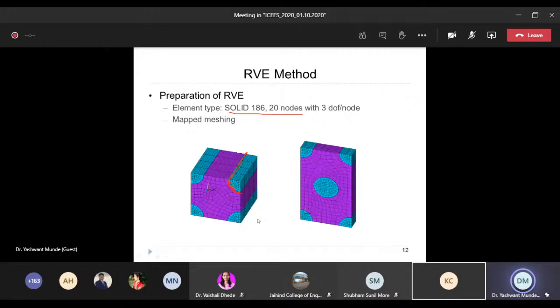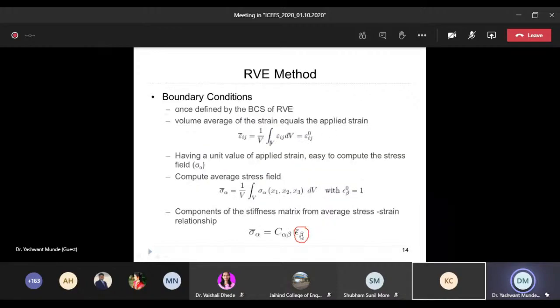And in a unit strain problem, we directly know the stress induced in each element, so then we can find out the value of C alpha beta. So what is the value of this strain? Strain is unit. We can know the stress induced in the RVE, and from the stress induced in the RVE, we can directly calculate the stiffness matrix coefficients. So important after solving the boundary conditions is to get this C alpha beta, or C, also called the CIJ matrix. That is the stiffness tensor matrix. Okay, so that's what you have to calculate.